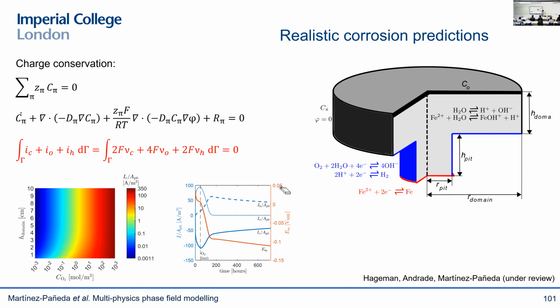We can also do other things. For example, all the experiments in corrosion and also the simulations assume that you apply an applied potential, because you don't want to wait 50 years for your sample to corrode in the lab. You want to accelerate the corrosion process. But there's no reason for that. I mean, in reality, this is not what happens. Very often, corrosion occurs in isolation. So we can take our model and, instead of doing whatever COMSOL does, we can define the applied potential as a degree of freedom. We can impose this charge conservation equation, and then we can obtain the natural result of the metal potential, basically.